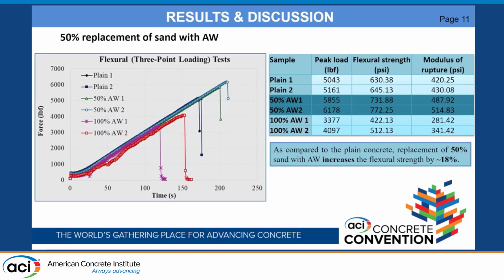So now moving on to the 50% replacement. This was the part of the project that I was mainly on with the alumina waste. We saw very good numbers here. You can see that we saw about an 18% jump in flexural strength compared to the plain samples. So that was good to see. We had much better samples this year. We had a lot more uniform mix, so to speak.